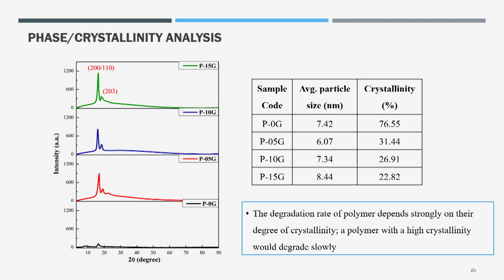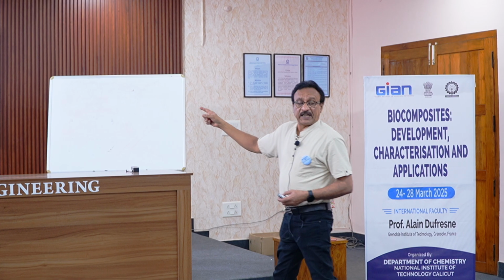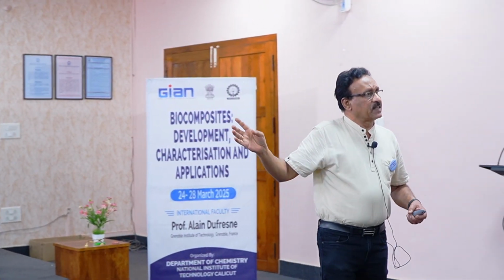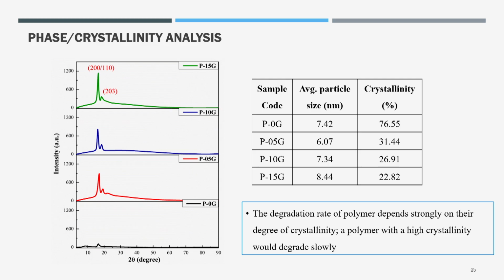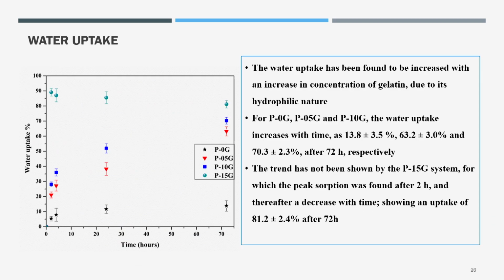But if PLA gelled into gelatin, functional group signatures would be broadened and shifted to the right-hand side. That does not happen. Then the X-ray evidence. PLA has a signal, gelatin has a signal, but gelatin has less signal, so you can see that without gelatin the system is highly crystalline. There is the Scherrer equation, and a lot of calculations we can do for XRD. From there you can see that without gelatin, PLA is 76% crystalline. But with the introduction of gelatin, the crystallinity decreases, so the system tends to be amorphous in nature.